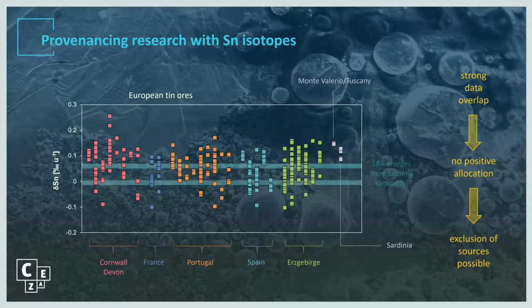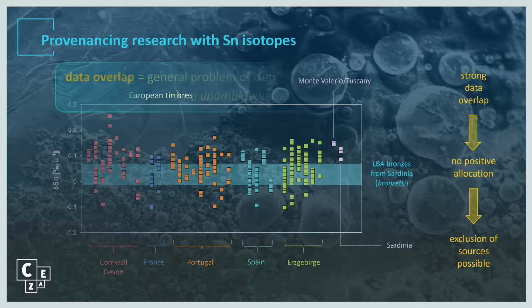And here is tin isotope data from a recent study of bronzes from Sardinia. The blue bar shows the variation of the tin isotopes in the bronzes. And when we compare it with the local ores of Sardinia, we see there is a mismatch between the ores and the Sardinian bronzes. And this is a very clear indication that the local sources of cassiterite have not been used, so the tin for these bronzes must have been imported, must have come from abroad.